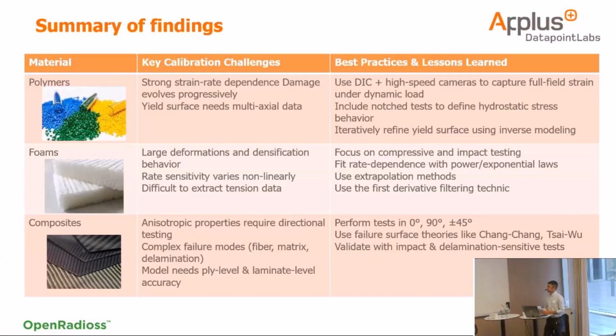So, a brief summary of these three models. For polymers, as I said, they are strongly strain rate dependent, and the damage evolves progressively. Here, what I usually recommend is to use as much DIC as you can, because it's really the key to having a really good set of data that you can then play around with, tune your model, and learn a lot from. It's important not only to stick to just tensile or compression and so on. So test as much as you can in terms of notch tests, different strain rates, and so on.